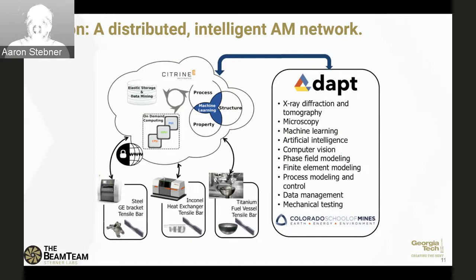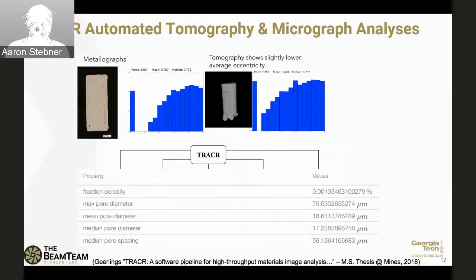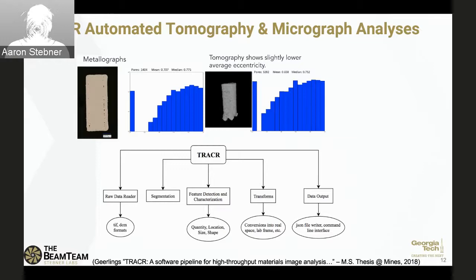So if we go to the next slide. One of the first things we needed to do was be able to automatically analyze a lot of our data, in this case porosity data. If you want to support machine learning, you need more than 10 data points. You'd ideally have thousands to millions of data points. So if we're going to start running thousands of X-ray tomographies, and each one may have thousands of pores within it, we need to be able to automatically analyze those without having a student visualize each data set, count the number of pores, say what their sizes are, and draw boxes around them in some software interface.